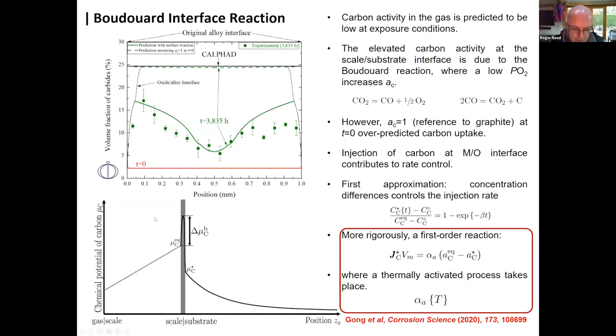And this graph on the bottom left isn't quite right. I don't really think it's perfect, but you can see here that the net idea is that there's an activation energy over which the carbon has to overcome before it can enter into the steel. And probably this activation barrier isn't solely an interface, maybe extends into the oxide, we think, or I think, to a degree.